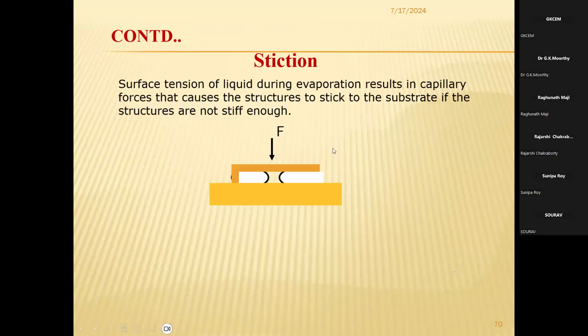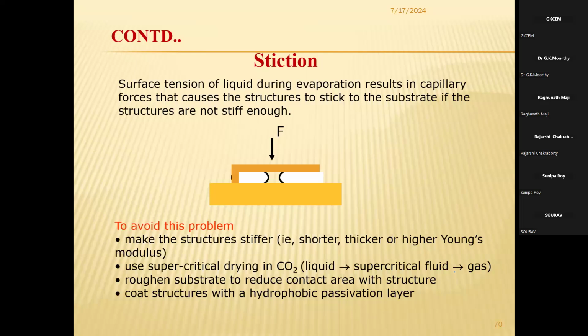So there is a stiction problem in surface micromachining. That is, the gap between the micro cantilever and the silicon is very, very small. So if you wash it with water or with any chemical, there is a problem of stiction. That means chemical molecules may get stuck between the structure and the silicon, and it is not an easy task to remove the molecule that is stuck in between the two layers.